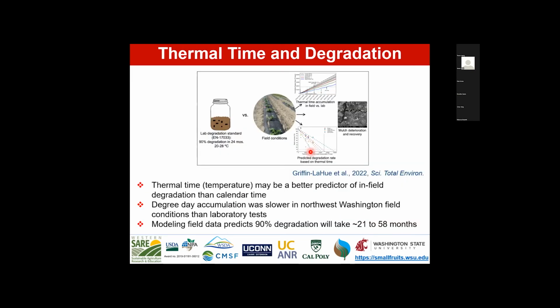And then I'd like to highlight some work also that has come out of Washington State University looking at thermal time and its effect on degradation. And I think this is really shedding some light in terms of how we think about degradation in a field environment. So what this study found is that thermal time or temperature might be a better predictor of in-field degradation than calendar time. So if you remember, we have standards like EN 17033, which has 90% degradation or greater within 24 months at temperatures between 20 and 28 degrees Celsius.